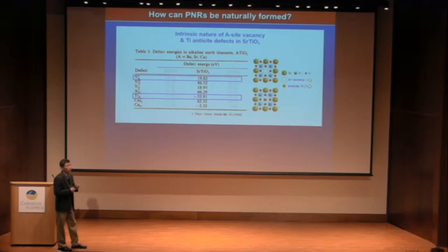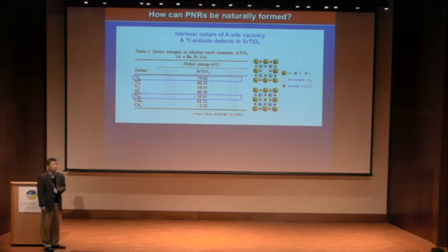Yeah, I don't know if people can hear you. So. If I look at this table, the defect of anti-site titanium holds charge +2, effective charge, which means that the formal charge is +4 in the A site, and then you just build up a global charge on the sample. It has to be compensated by something. If you just calculate the energy of this single defect, it makes no sense. It has to be associated with something else.